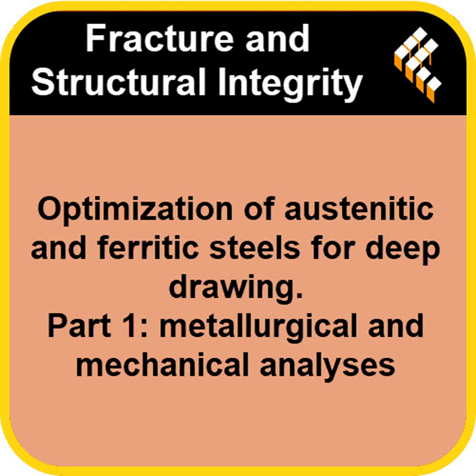Okay, easier sliding is good. And punch speed, faster or slower? Slower was better. Running the punch slowly, at 4.3 millimeters per minute, gave a better Erichsen index than running it fast, at 120 millimeters per minute. Why would slow be better? It gives the material more time to deform. At the microscopic level, plastic deformation involves things called dislocations moving through the crystal lattice. Slower speeds make it easier for these dislocations to move and rearrange, accommodating the stress without causing a failure. So slow and steady wins the race, but lubrication is the car you're driving. Well put. Speed and pressure matter a bit, but they're minor compared to the choice of material, and especially the right kind of lubrication.